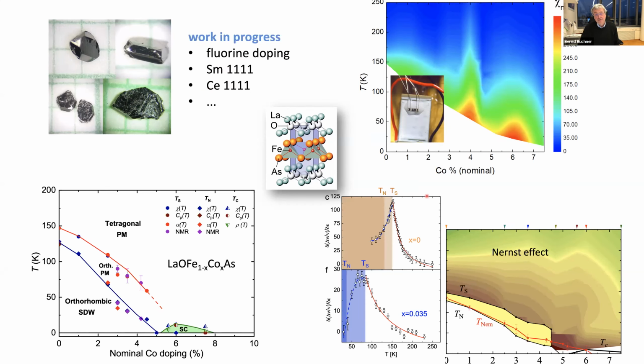And then at the end, I've shown you some first results on strain derivatives of more complex transport properties like the Seebeck effect and Nernst effect. All of them strongly depend on the lattice, which shows that the nematic instability is very crucial for the electronic state here. And I think that also gives us first new approaches to understand this coupling, which seems to be band selective, and which seems to be very strongly connected to the Fermi surface.